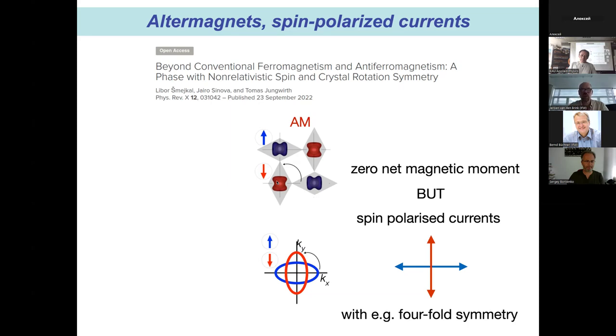So that makes it clear that if I go from one sublattice to the other sublattice, the elongated ones are red. Here this one has more red spin. And now I rotate, then this one gets more blue, more upspin. So another way of looking at it is that in this altermagnet at least, you get a magnetization of the rutheniums, and this magnetization induces a magnetization on the oxygens, and these oxygens are rotated with respect to each other if I go from one sublattice to the other sublattice. This is the same reason I get the spin splitting.